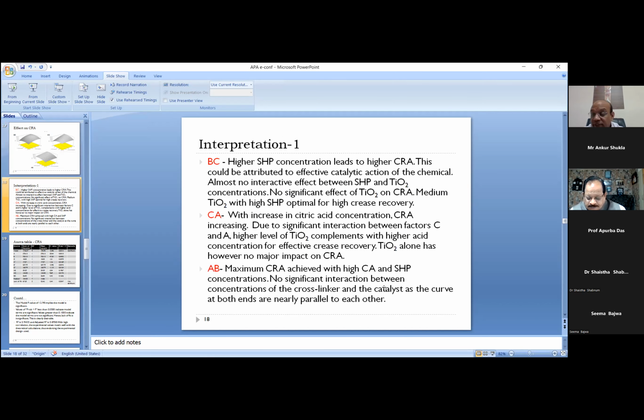So this is the interpretation, the one that I just told you. High SHP concentration leads to high CRA, and this could be attributed to the effective catalytic action of the chemical, with almost no interactive effect between SHP and TiO2 concentrations, and no significant effect of TiO2 on CRA. Medium TiO2 with high SHP is optimal for high crease recovery. Then this is the CA interaction, the second one that I told you. With an increase in citric acid concentration, there is an increase in the crease recovery angle. And coming to the third one, you have the maximum crease recovery angle achieved with high citric acid concentration as well as high SHP concentration.